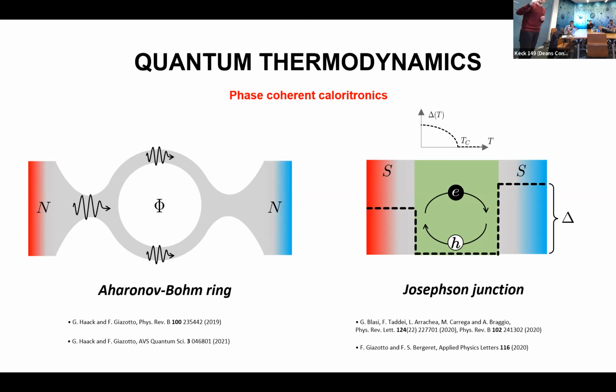What happens is that if you compute the transmission going left to right, summing all the possible paths you can have, it is different from the probability going from right to left only if you add this phase. If there is no phase, there is always a coherent destruction of waves. Instead, when you add this difference in the dynamical phase acquired by electrons, which is tuned by the Josephson bias in the case of the Josephson junction, but is the same as the magnetic flux in the AB ring, you're shifting the electron waves versus the hole waves in one way from left to right, and in the other way from right to left.